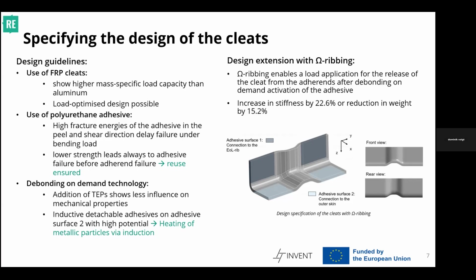Second, I recommended polyurethane adhesives, because of their high fracture energies in both peel and shear directions, which delay failure under bending loads. And at the same time, their lower strength ensures that the failure always occurs within the adhesive layer rather than damaging my adherent. This is a key advantage of the design because it always enables reuse of the structural components after debonding on demand separation.